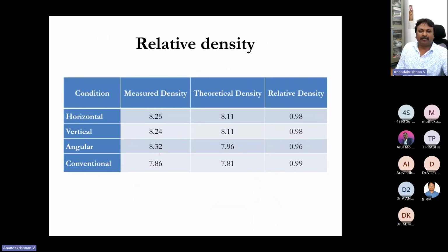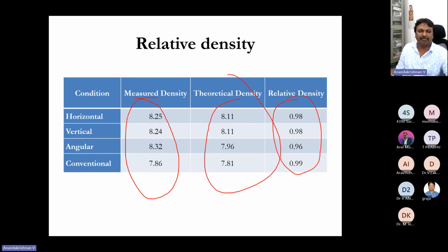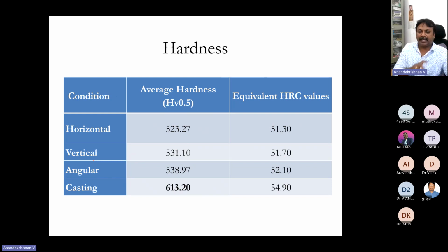Based on that, we also looked at the measured density and the theoretical density. We found the relative density of the component printed horizontally, vertically and angularly, and then we compared it with the conventional investment cast component. See, the component I told you about, that starting nozzle, is a complicated shape. It was earlier made by the investment casting technique. Because of its complicated or intricate shape, when 100 components were made, they found only 8 components qualified the dimensional measurement. So they thought of going for powder-based additive manufacturing. And myself, along with another professor, Dr.